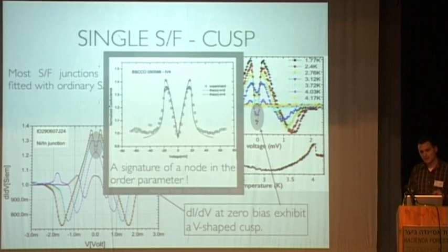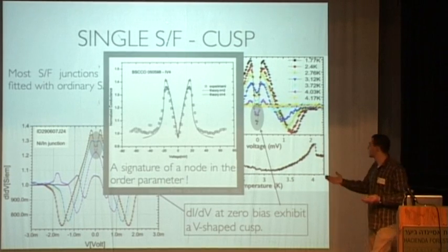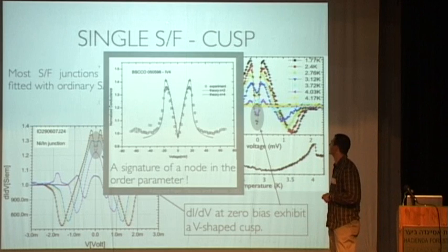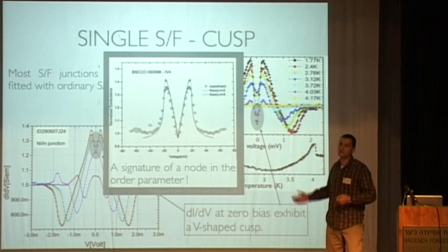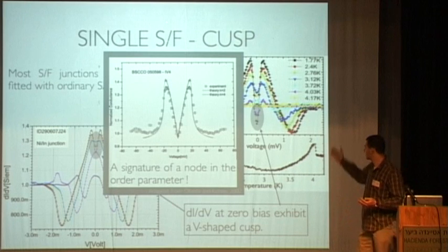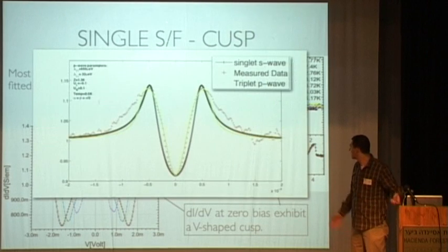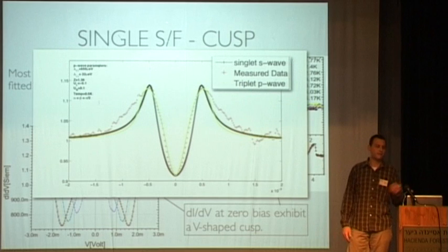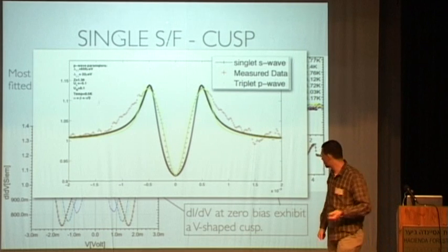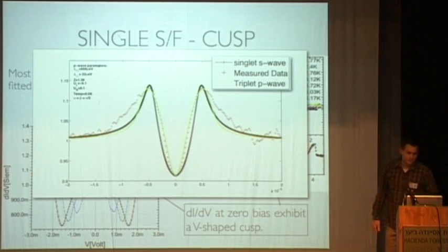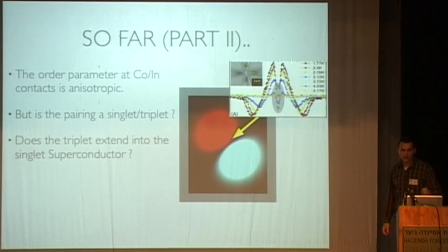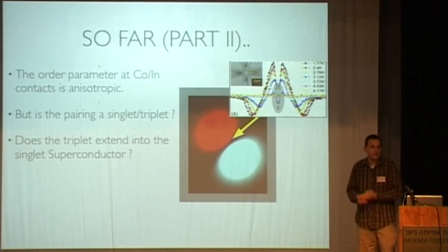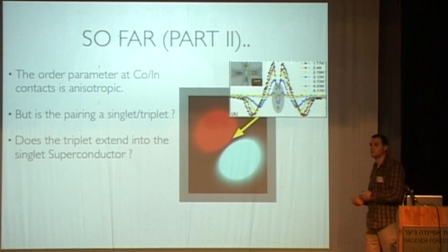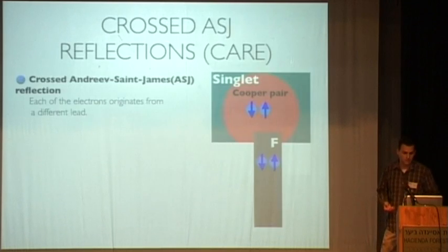We don't know yet. And this is a comparison with a known anisotropic superconductor. In this case, it's BISCO. It's a high-Tc superconductor. And this is a similar cusp. Now, we can also do mathematics and fit the conductance with theory, and it works. So far I showed you that the order parameter at the contact is anisotropic. But is it singlet or triplet, and does it extend inside the superconductor? We have to find it out.